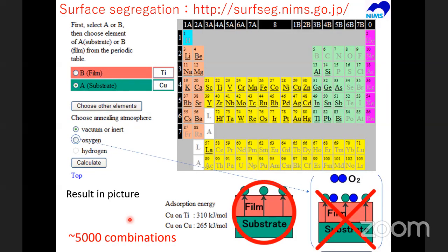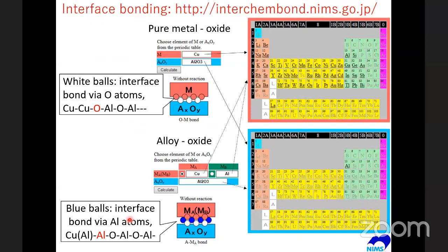And for interface bonding, the interface between pure metal and oxide, or binary alloy and oxide, is given. Again, choosing the metal element or oxide from the periodic table, it will give the result by pushing calculate. For pure copper with an aluminum oxide interface, oxygen is terminating. But if the aluminum is alloyed with copper or another metal element, the interface becomes aluminum, which we already proved by experiments.